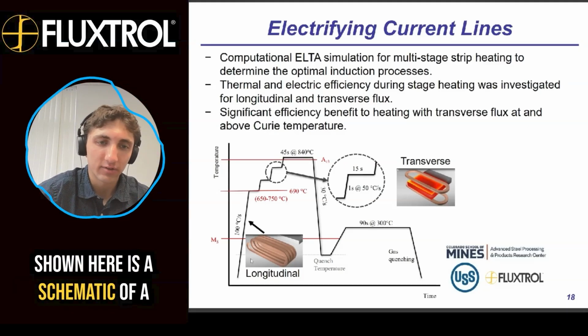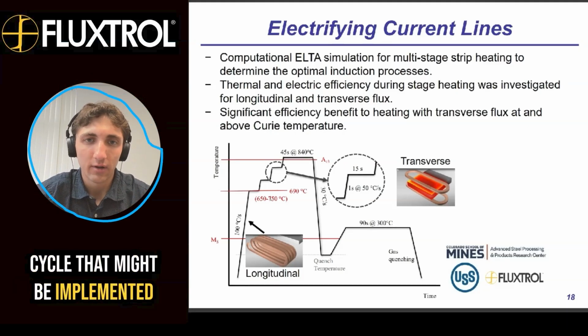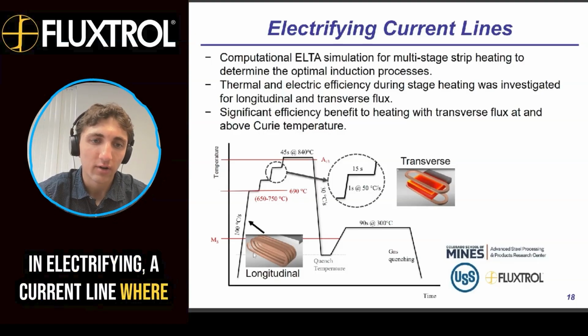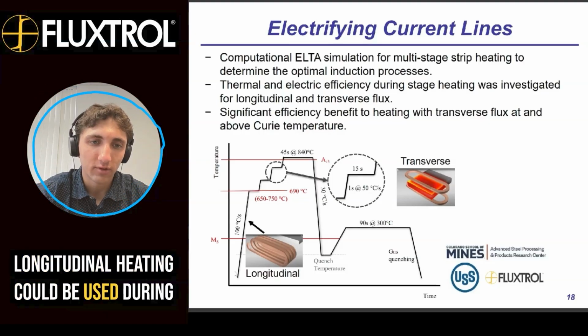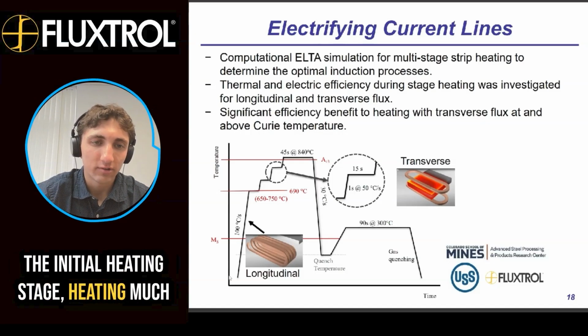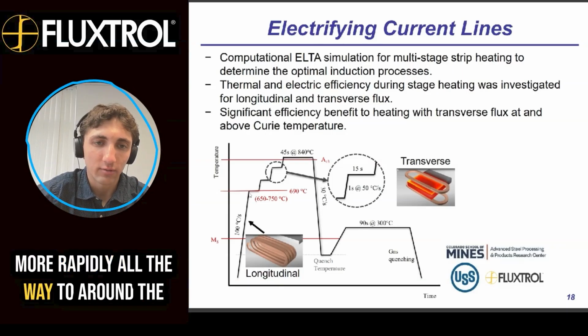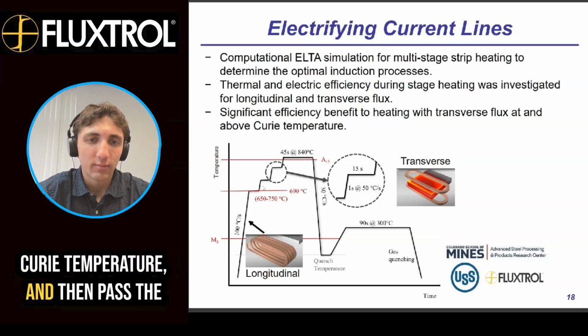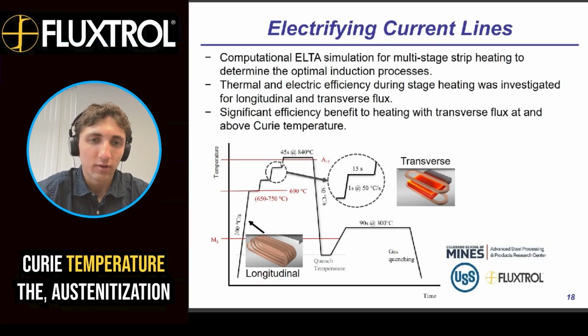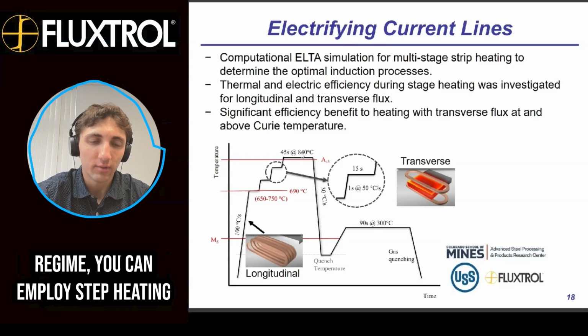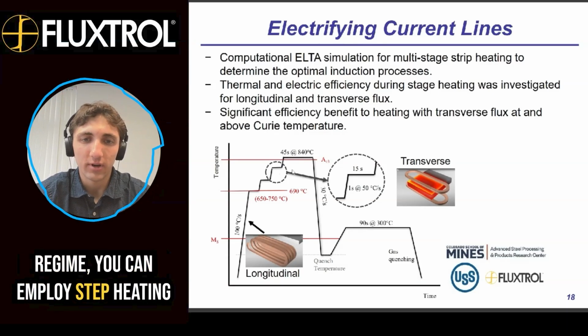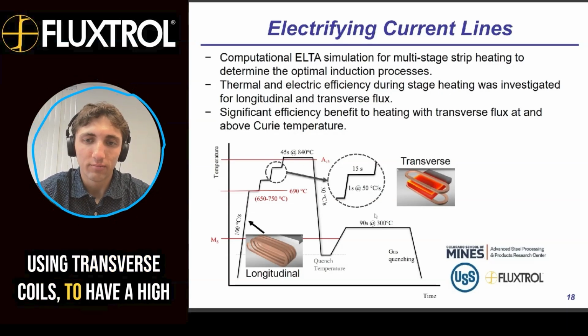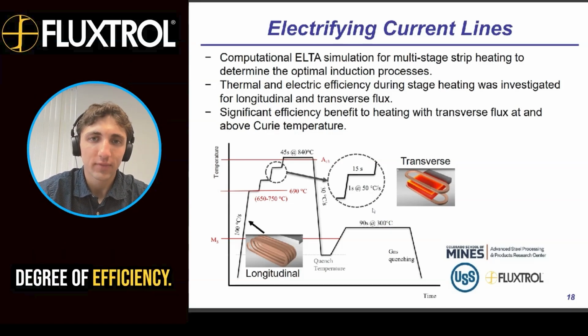And shown here is a schematic of a cycle that might be implemented in electrifying a current line where longitudinal heating could be used during the initial heating stage, heating much more rapidly all the way to around the Curie temperature, and then past the Curie temperature into the austenitization regime. You can employ step heating using transverse coils to have a high degree of efficiency.